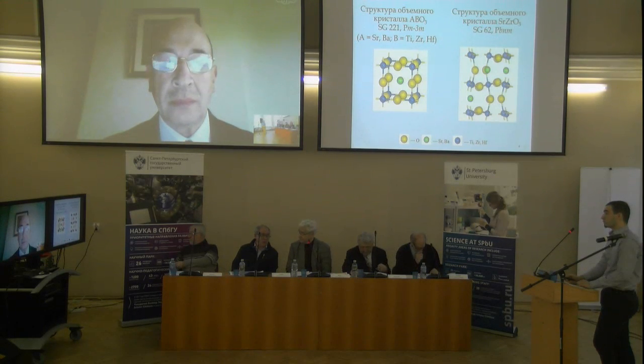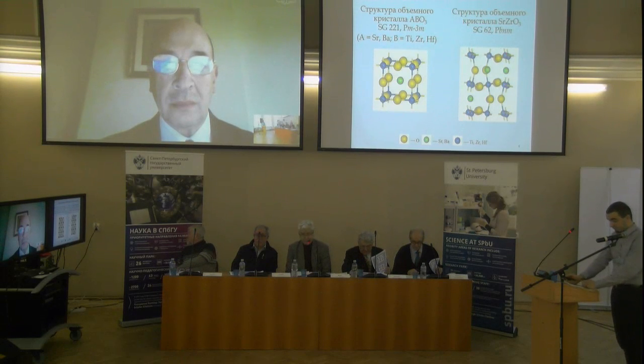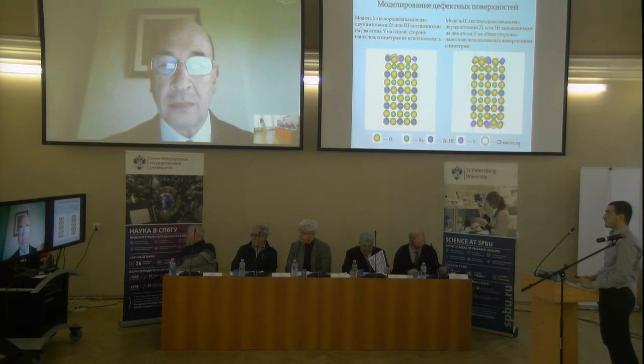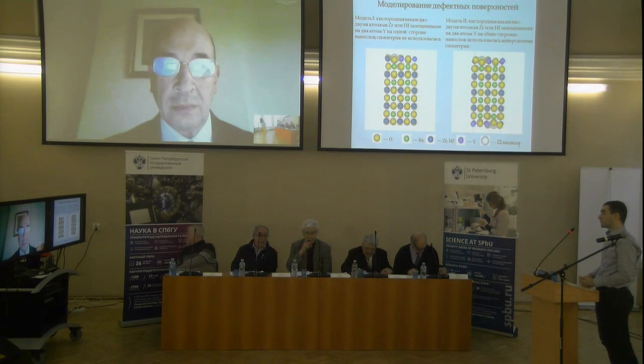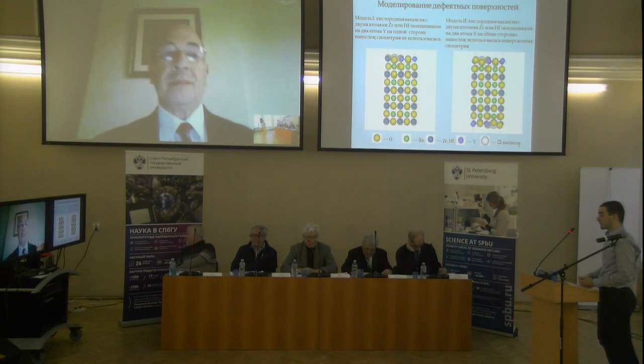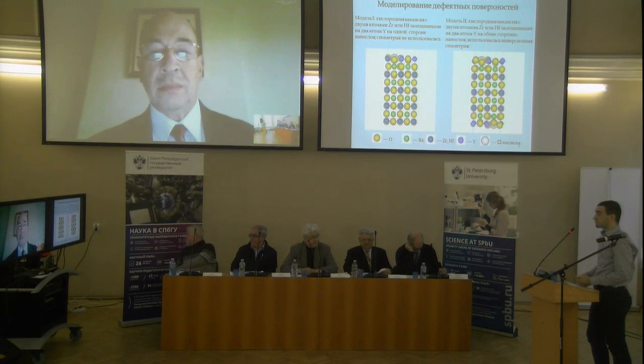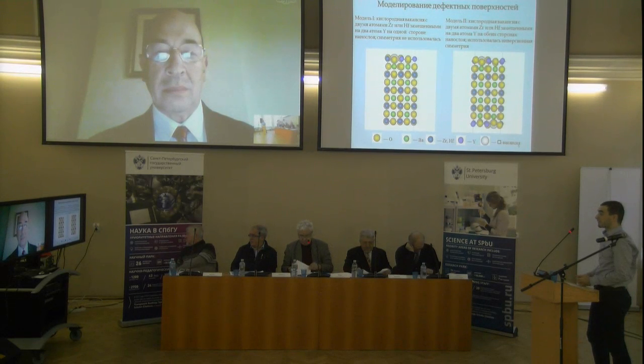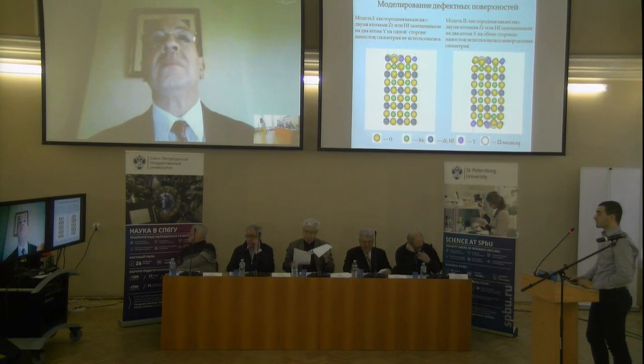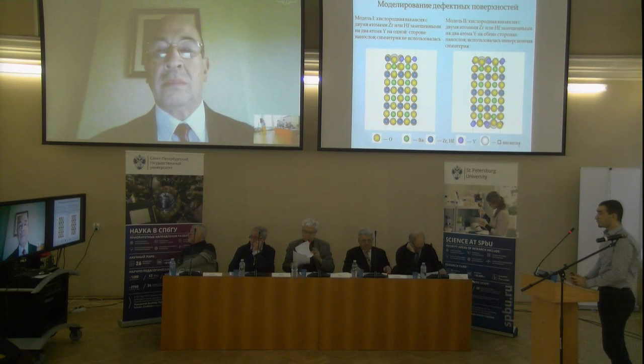Perovskites can exist in different phase modifications. The cubic structure inherent in most perovskites is characterized by the space group Pm3m. For the strontium zirconate SrZrO3 crystal, the orthorhombic modification with the space group Pbnm was also considered. Bulk crystals were used primarily as test systems to verify the reliability of the chosen calculation method. The calculated lattice parameters, moduli of elasticity, atomization energies, and the widths of forbidden bands agree well with the available experimental data.